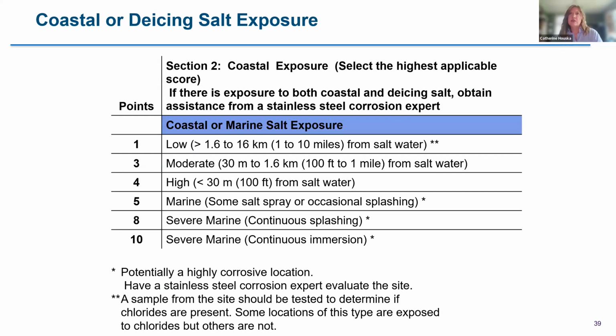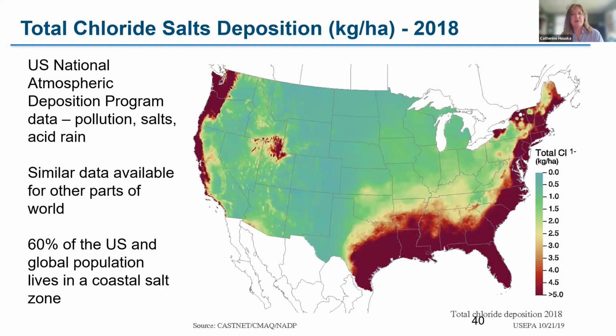So with coastal or deicing salts, the distance from the water will determine how high that salt concentration is likely to be on surfaces. Part of also suggesting that you look at the National Atmospheric Deposition data is that I've provided general guidelines here. There are locations that are different, where higher levels of salt travel further inland. Generally, it's the areas with salt spray in the first 100 feet that have the highest levels. And then once you get past that, the salt levels start to drop considerably. But there are exceptions, which is why if you can have access to data, and we certainly do in the United States, I suggest you look at it.